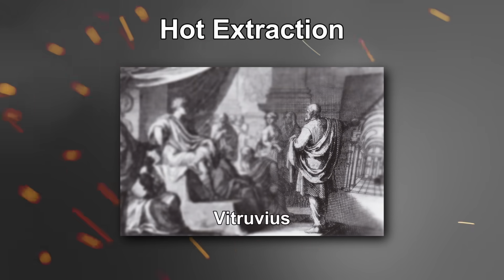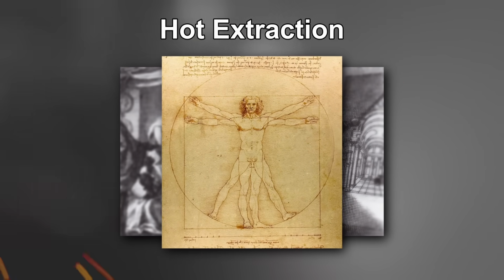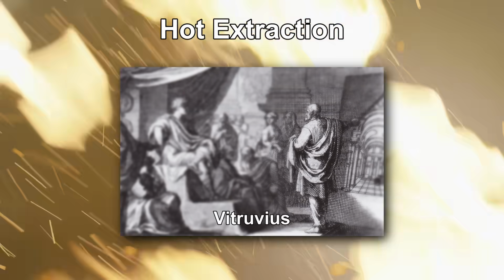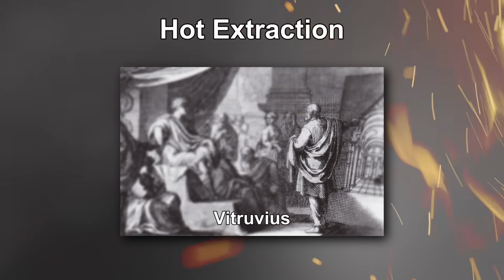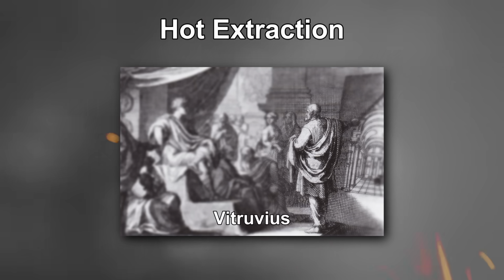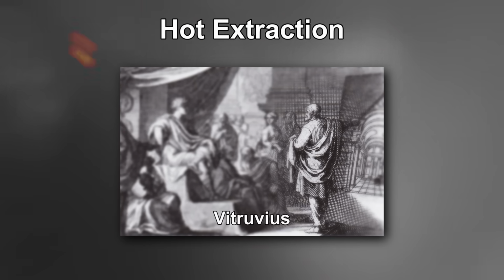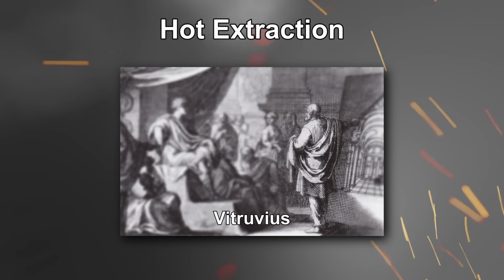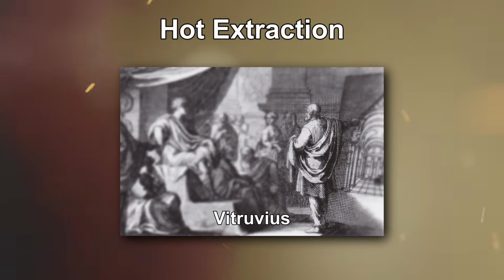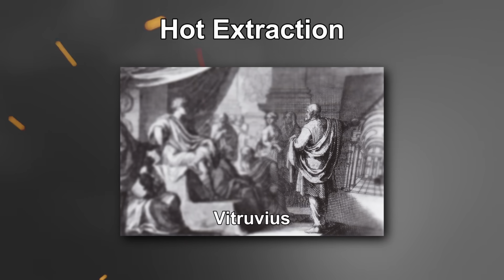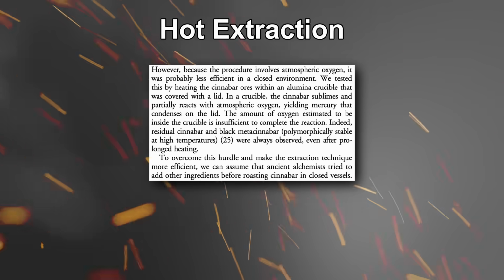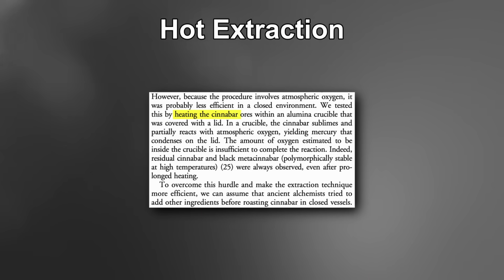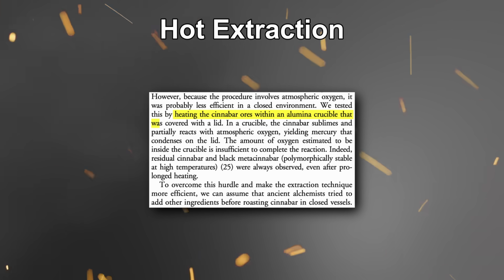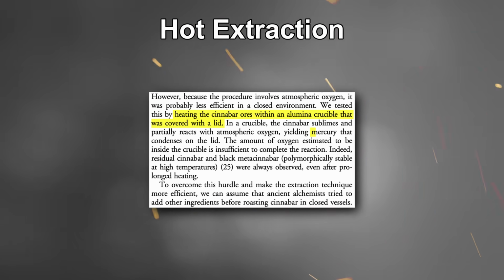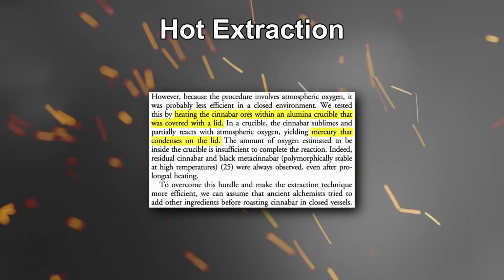The first of these is just the reaction between mercury sulfide and oxygen to form sulfur dioxide and mercury. In the 1st century BC, Vitruvius, by whom Da Vinci was inspired to draw his Vitruvian Man, described how, when unrefined cinnabar was baked in a kiln to dry it out, mercury was always found on the floor of the kiln. So it seems like the simple act of heating cinnabar led to the formation of mercury. The researchers tried to recreate this method by heating synthetic cinnabar within an alumina crucible that was covered with a lid and found that liquid mercury condensed on the lid of the crucible.